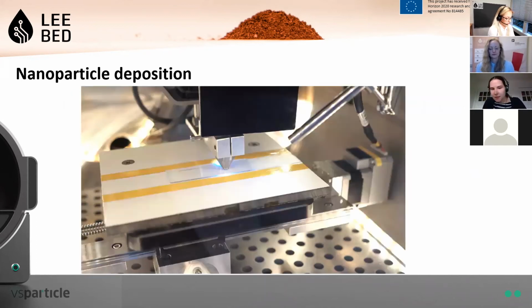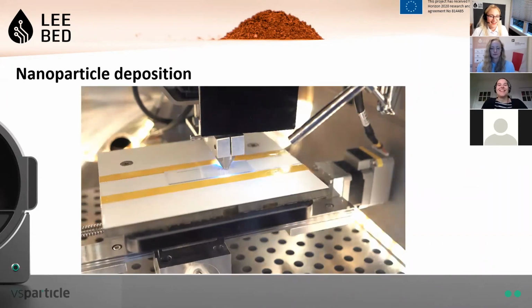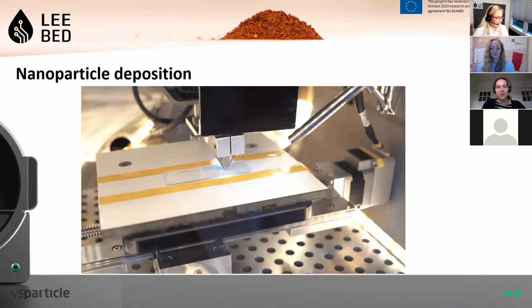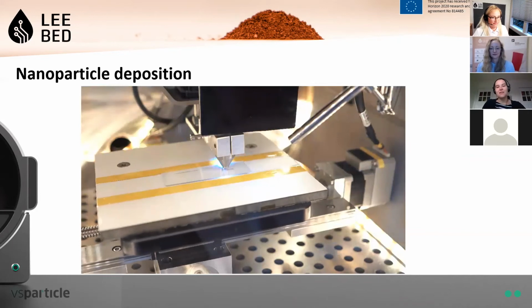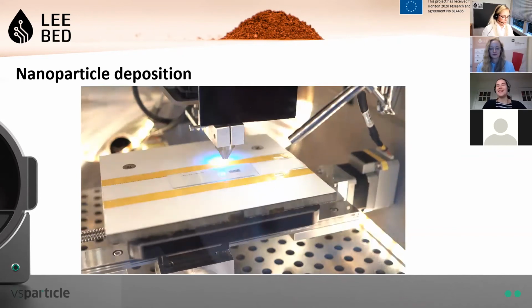And next, I want to show you a short movie. Here on top, you see the nozzle, below a glass substrate, and we print with, yeah, it moves. We print with gold. So in this movie, you see 4 gold lines that are printed. Or is it 5? I'm not sure. And this video is sped up by a factor of 3. So in reality, it takes 3 times longer. But then you just get a thinner or thicker layer if you vary the print time.